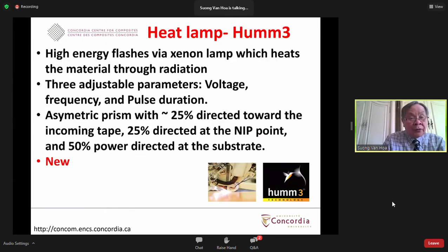And over the last few years, there came the heat lamp, the HUM3. It uses high energy flashes via a xenon lamp to heat the material through radiation. The 3 parameters are voltage, frequency, and pulse duration. The advantage of the heat lamp is that they can direct the heat in different locations: 25% toward the incoming tape, 25% to the nip point, and 50% directly at the substrate. The disadvantage is that it's fairly new, so we need to study and learn more about it.